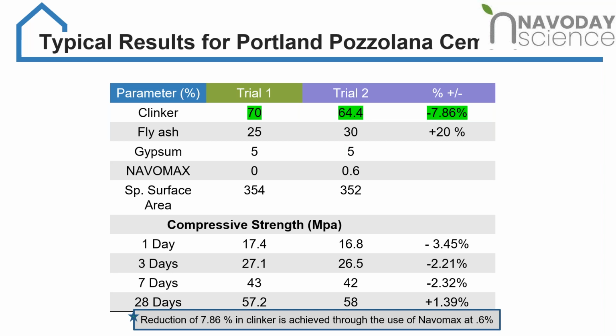So this is once again trial results for Portland Pozzolana cement using Navomax at 0.6%. The same case here: even though the one-day strength is marginally lower compared to the control, your 28-day strengths are marginally higher. And a reduction of 7.86% of clinker is achieved through the use of Navomax at 0.6%. Next slide, madam.